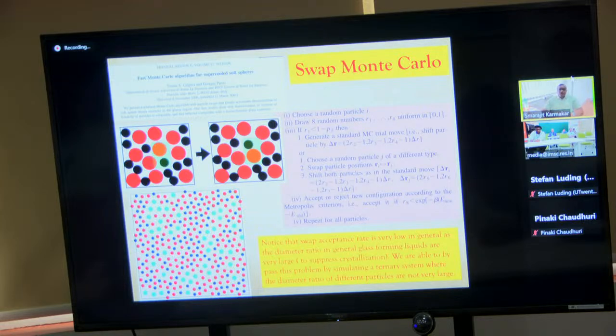So one can actually make progress, and I want to give credit to Giorgio. When I was coming back from Rome, he suggested, why don't you try using ternary particles, where you have small, medium, and large particles, and the swap will then be done in a sequential manner. A small and a medium can be exchanged easily, and a medium and a large can be exchanged subsequently. This will enhance your acceptance rate by a significant amount, and one might be able to equilibrate the samples much faster.